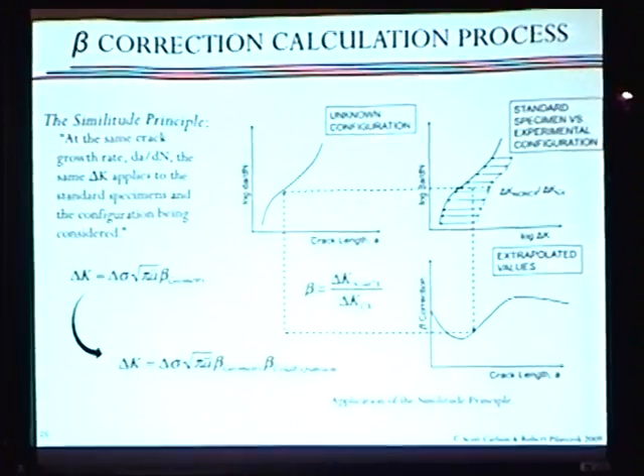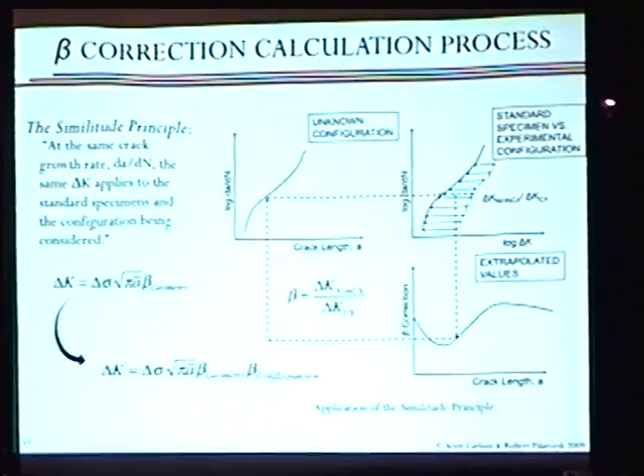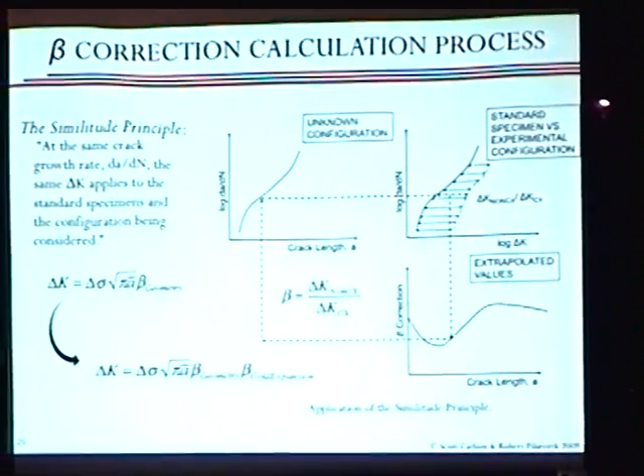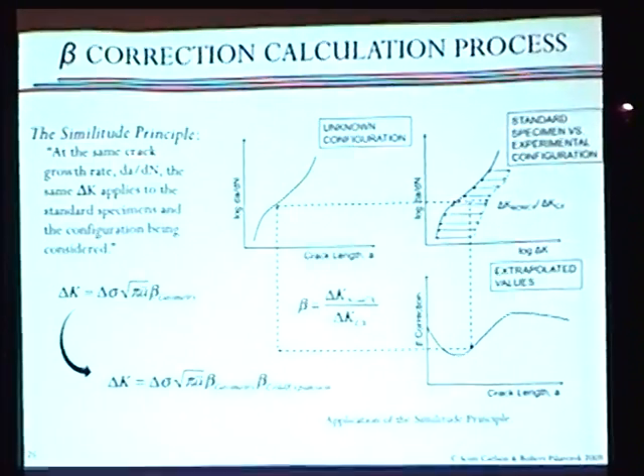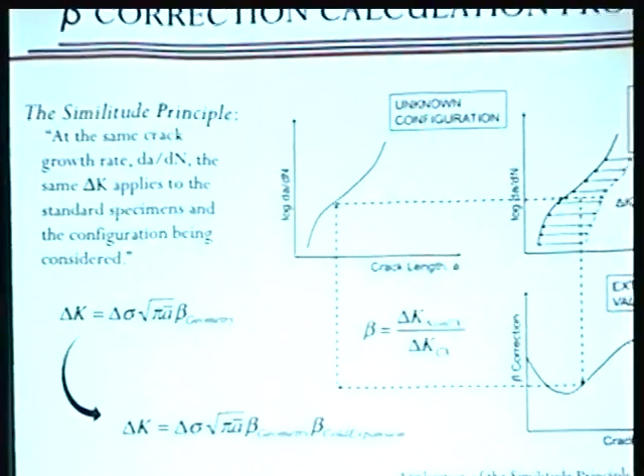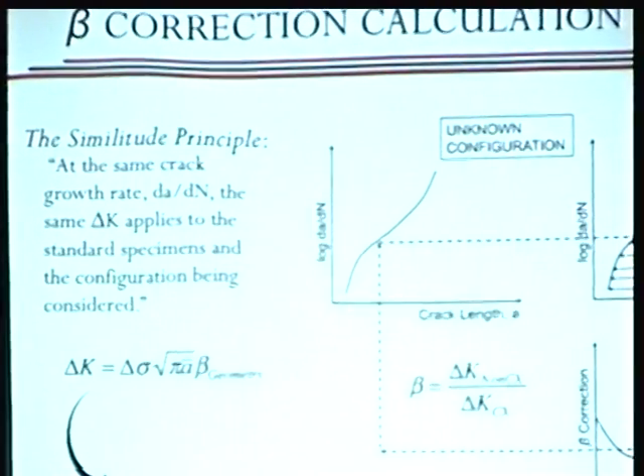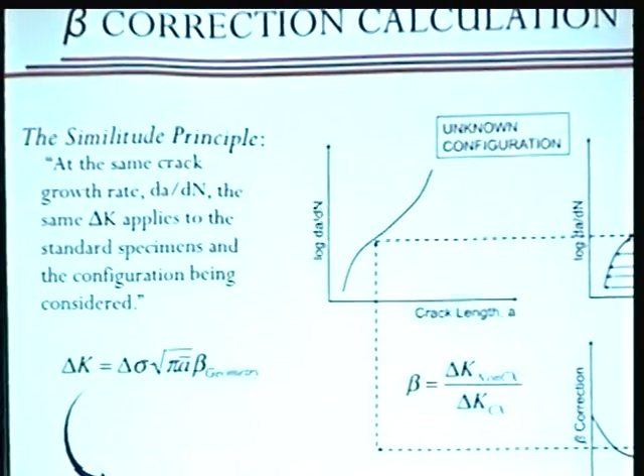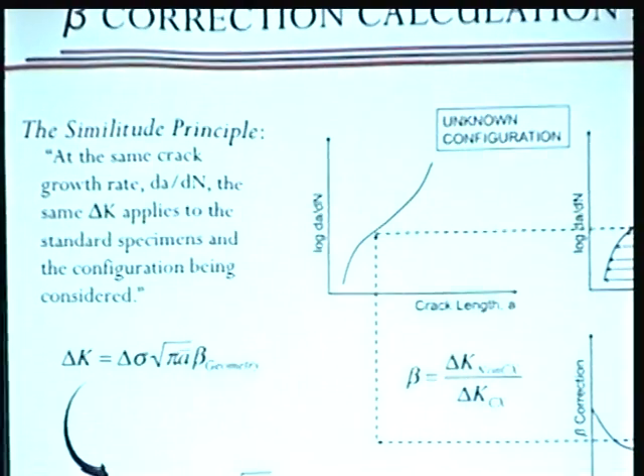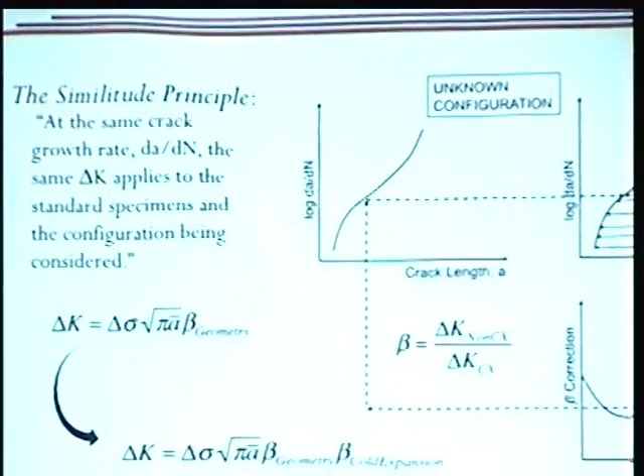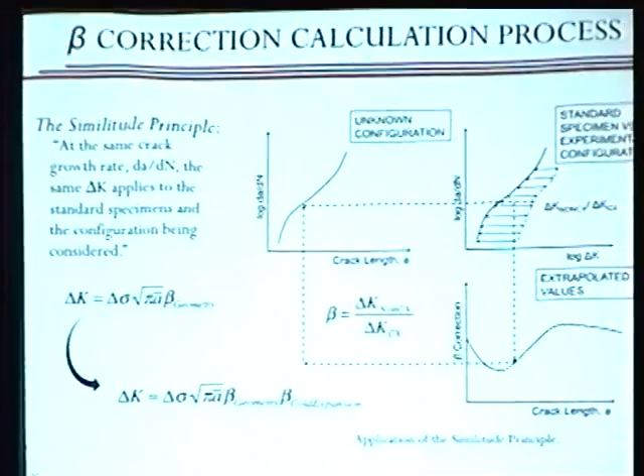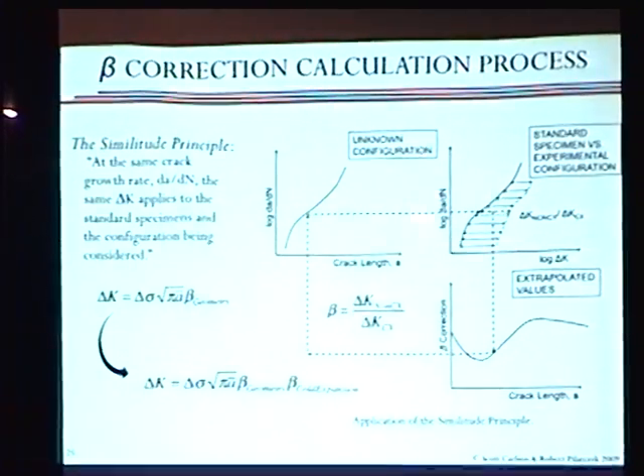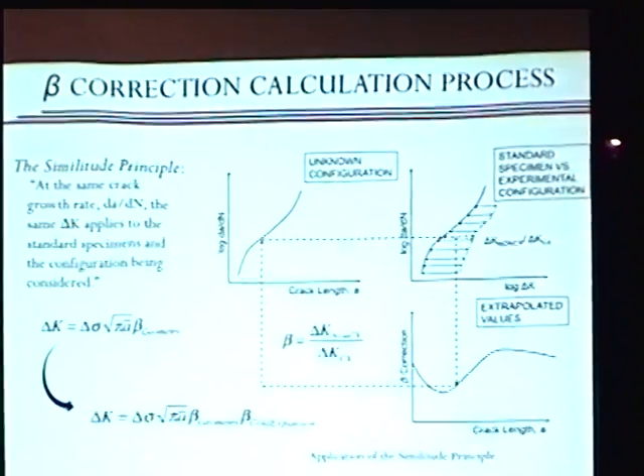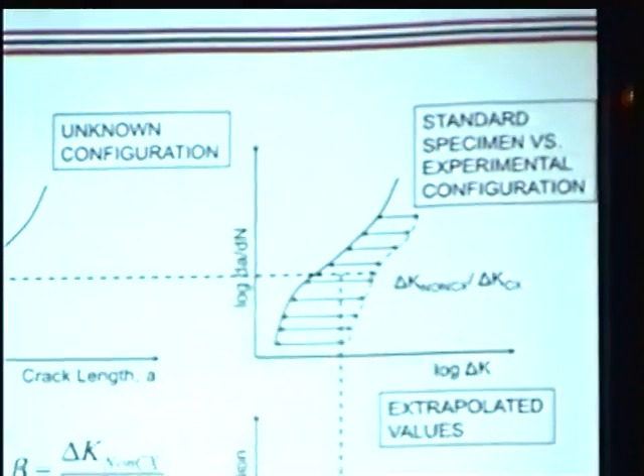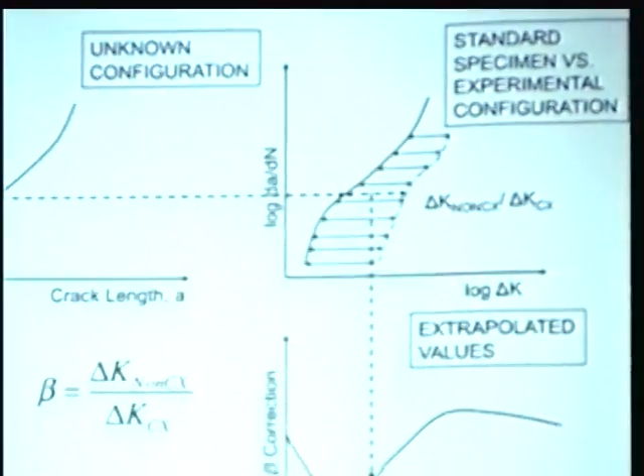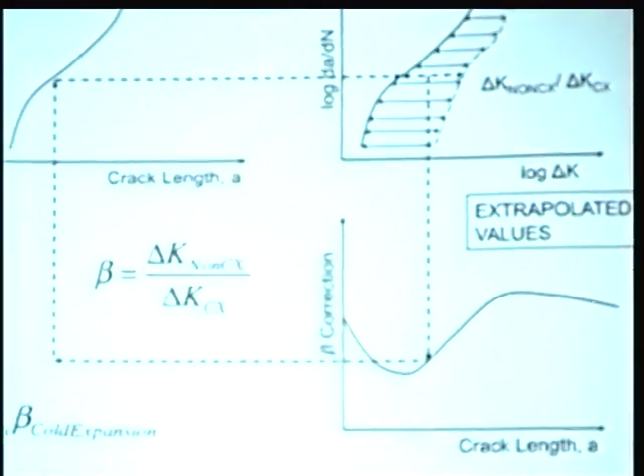So how did we do that? Well, it's all based on the similitude principle, which says that for a given crack growth rate, if I have two components that are exactly the same, the stress intensity at the crack tip is the same. So if you see the crack propagating at the same rate, the stress intensity at that crack tip is exactly the same. And based on that, we can compare the two and pull out a beta. For every single specimen, we understood the crack growth rate versus crack length from our test data. We also understood crack growth rate versus delta K, from our test data and our FEM models. From that, you can calculate the difference as a result of that process.